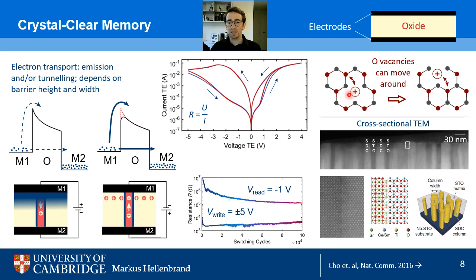Now different elements such as oxygen or nitrogen or whatever you can think of, they attract or bind the cloud of electrons to the nucleus with different strengths. And by combining certain materials, oxygen and something else, the oxygen vacancy carries a relative positive charge because the surrounding atoms attract electrons stronger than the oxygen vacancy. Okay, so this is where the directionality of the oxygen vacancy movement comes from. Positive voltage on one side pushes away the oxygen vacancies which also carry positive charge. Negative voltage at the same interface draws the positively charged oxygen vacancies towards them.